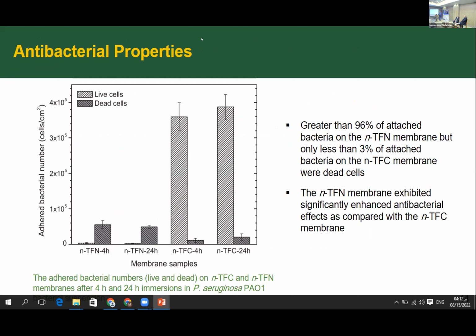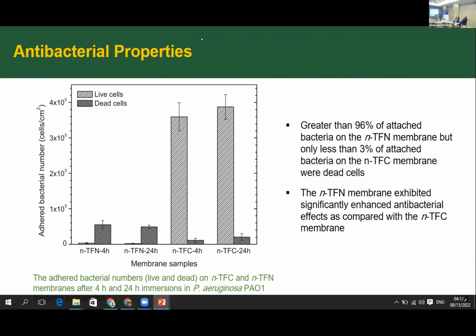For the antibacterial properties, as you can see from the figure, greater than 96% of the attached bacteria on the NTFN membrane, but only less than 3% of the attached bacteria on the NTFC membrane, were dead cells. And that tells us that the NTFN membrane exhibited very strong enhanced antibacterial effects as compared to the NTFC membrane.